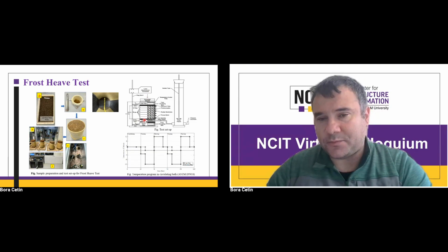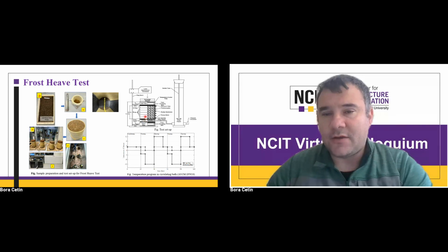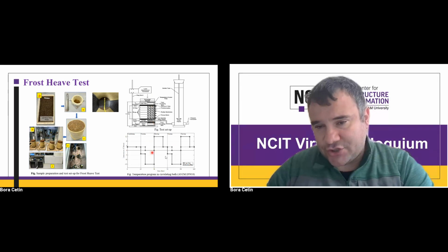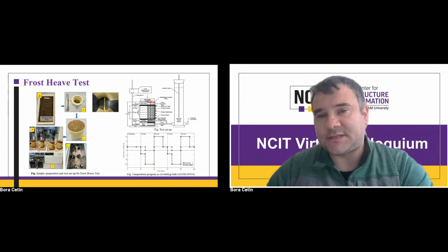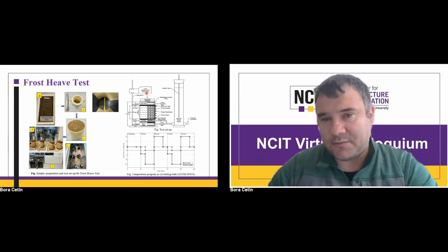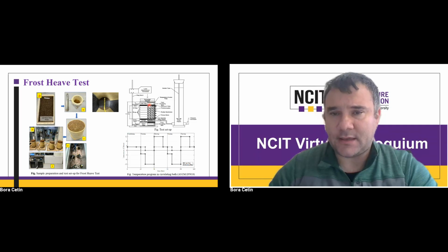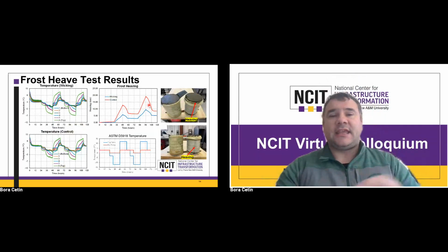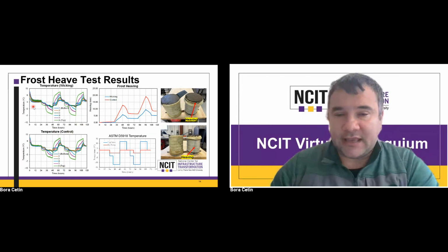And we keep the bottom plate always warm at 4 degrees Celsius. And we monitor this temperature regime, how the specimen heaves and how much it thaws. And we measure displacement through lasers that are put on top of each specimen. And here, the red, I won't again go into much detail.